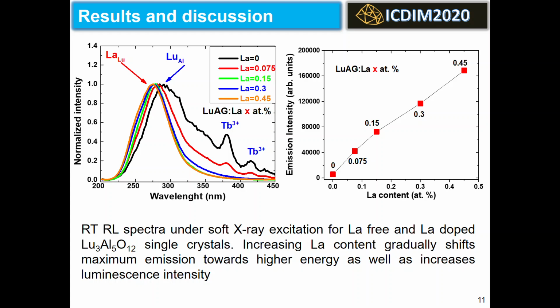The dominant luminescence in the ultraviolet spectral range in the undoped sample has lutetium-aluminum antisite defect origin, whilst in lanthanum-doped samples, the ultraviolet emission is caused by both lutetium-aluminum antisite defects and lanthanum-lutetium defect centers. Both kinds of centers can localize and bind charge carriers, followed by the formation of excitons. Their radiative recombination causes intense luminescence in the ultraviolet spectral range. In undoped and slightly lanthanum-doped crystals, terbium-3+ trace impurity luminescence is also observed.